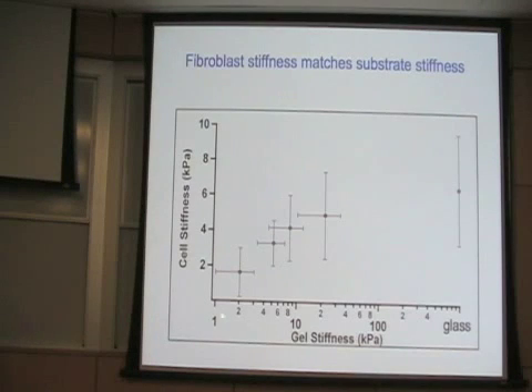If we change the substrate stiffness and look at how the cell's own stiffness depends on the substrate stiffness, for fibroblasts, mesenchymal stem cells, astrocytes, many other cell types, but not all cell types, the cell stiffness scales with the gel stiffness up until a point where the cell can't get any stiffer. You can make this substrate as stiff as you want, and eventually the cell will peter out. But during a very large range of substrate stiffness, which is approximately the range in which organs actually are, the cell is tuning its own stiffness to match its substrate.